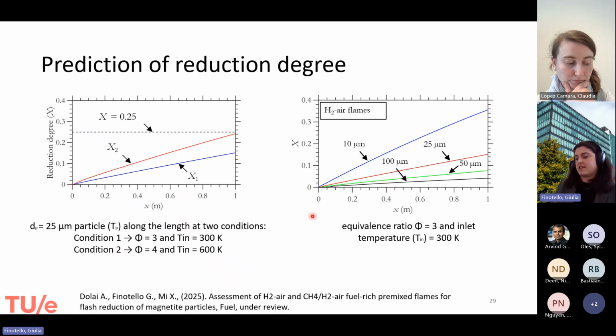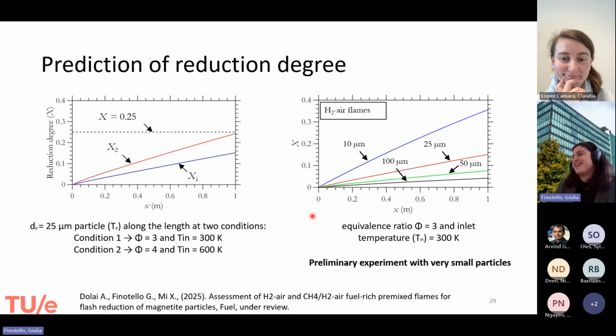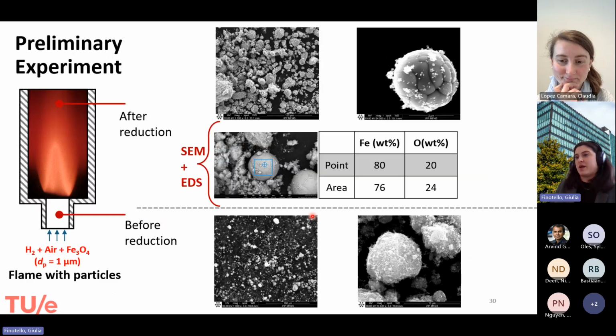And this gave us the idea for a very, very preliminary experiment, but I thought it was nice to share, because why not share new things? So we chose a very, very small particle. We don't use a drop tube because, as I said, we still don't have our drop tube. So we introduce some very small particles, of the order of 1 micron, into this flame, in this other reactor. So we introduce also hydrogen and air.